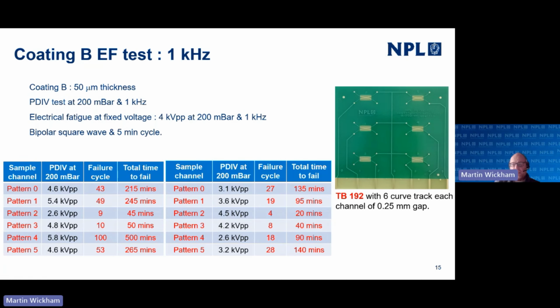This shows similar data for a coating. Again, a PCB conformal coating, coating B in this case. We're testing at 1 kilohertz, bipolar square waveform. This is a 50 micron thick coating. We're testing at 200 millibar now and at 1 kilohertz. And we've got a fixed voltage of 4 kVp.